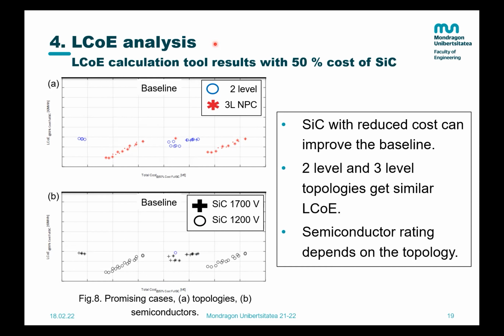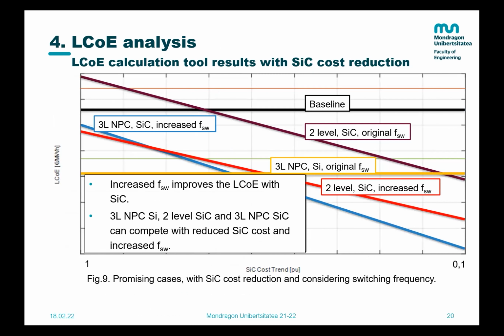So we decided to further study the impact of the cost in the silicon carbide semiconductors, and we also added the effect of the switching frequency, because remember that silicon carbide semiconductors are good at switching. So please focus on the brown line here, that is the 2-level topology with silicon carbide and original switching frequency. And now compare it to the two-level silicon carbide with increased switching frequency.